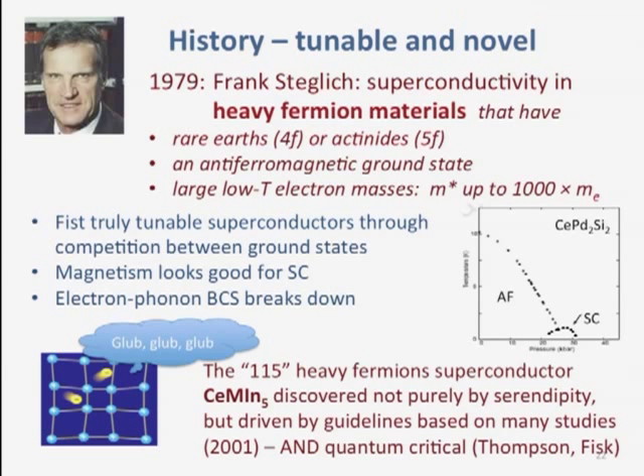And he also showed that it has this interesting phase diagram. It's antiferromagnetic here and has a superconducting phase here. And there's evidence of quantum criticality down there. These were the first truly tunable superconductors through a competition between ground states. In this case, the heavy electron state, and in this case, the Fermi liquid. For the first time, magnetism looks good for superconductivity.